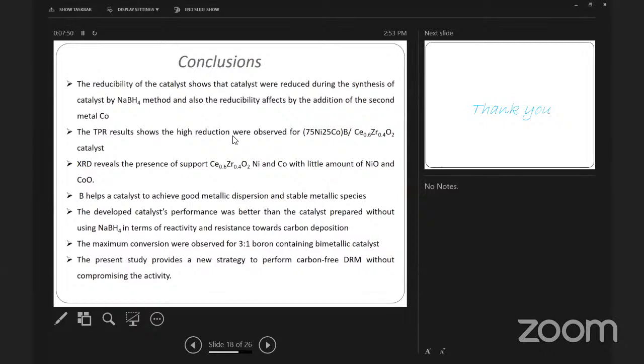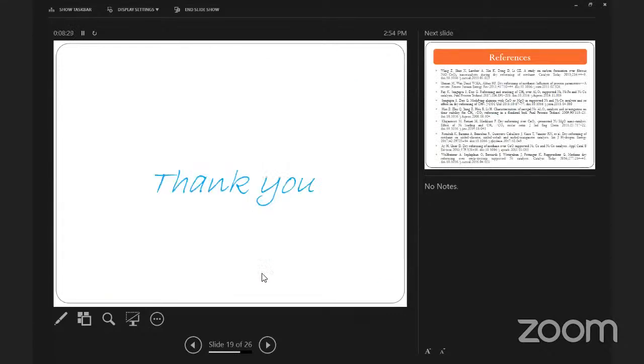From XRD, we got the metallic peaks of nickel, cobalt, and zirconia. The main thing is that with the boron catalyst, we have achieved good dispersion of nickel and good dispersion of boron, and we also got more activity. Maximum conversion we observed for the 75% to 25% catalyst, and mainly the carbon deposition was very low compared to the non-boron catalyst, especially for the bimetallic catalyst with 3:1 ratio. Thank you. Any questions, please?